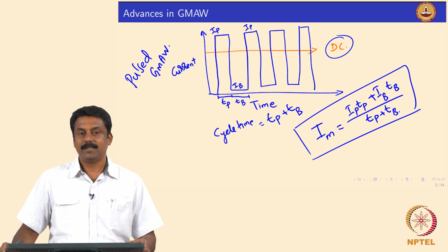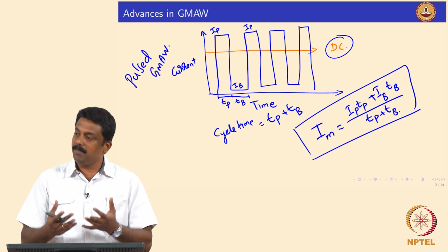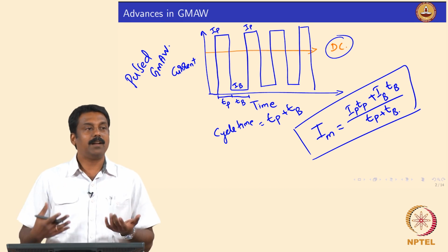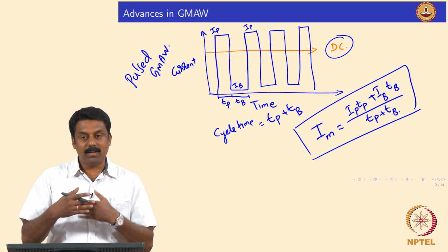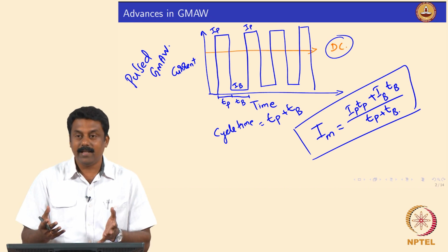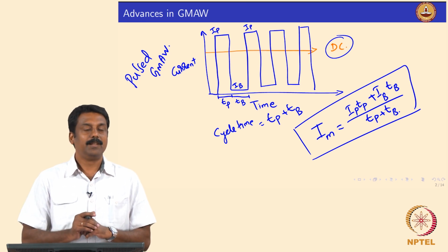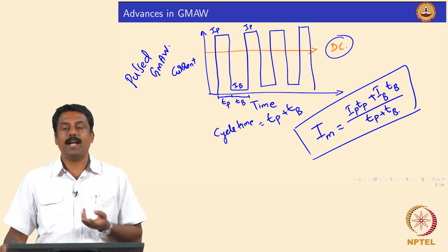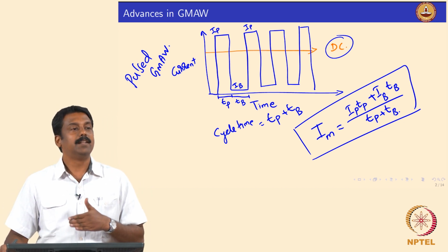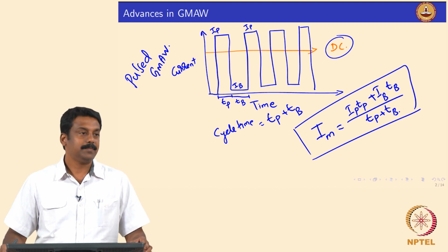case. That means that the amount of arc heat energy you generate will be lower than when you use a constant current, but by using lower current you can still achieve a spray transfer, isn't it. So, you can achieve a stable spray transfer by supplying an average current much lower than when you use a constant current throughout the welding process.